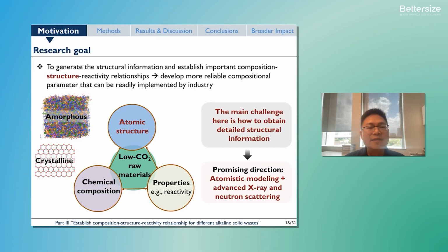Now, the challenge here is, how do we obtain detailed structure information on these low CO2 waste materials? Because the main reactive components in these materials are highly amorphous, meaning that the arrangements of atoms in these materials are highly disordered. This is different from a crystalline material where the atoms are highly ordered. In that case, we can use X-ray diffraction to determine the atomic structure.